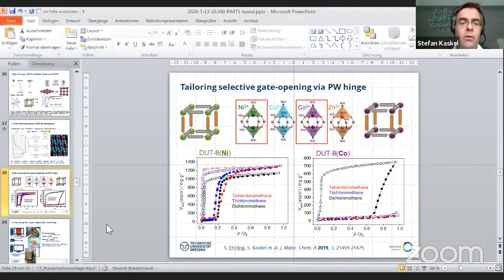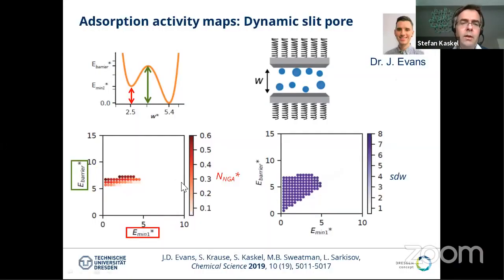structure is important. There is a theoretical paper by Jack Evans basically analyzing the impact of pore size. And this is a little bit difficult to understand easily, this slide. But here we have the bistable profile. And Jack Evans basically simulated this in a very general way, saying that we don't need a spherical pore, we only need a slit pore. And basically with the springs that are connected to the pore wall and the molecules inside the pore, we model a bistable energy profile, and we only model the energy between the local minimum. This is the energy difference between the local and the global minimum, and we vary what we call the activation energy. This is the barrier between the OP form and the CP form.